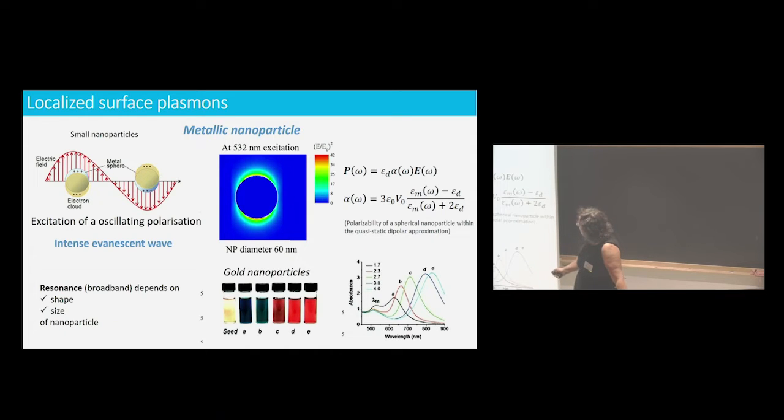In fact, when you look at what you have inside your ball, because the field is vertical and oscillating, you can see that when the field is in this direction, you have accumulation of minus charge here and plus charge here, and the reverse here. So you create a polarization of the system, an oscillating polarization, which can radiate. And the translation of this is an extra intensity.